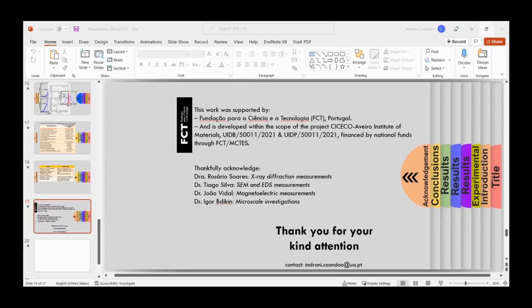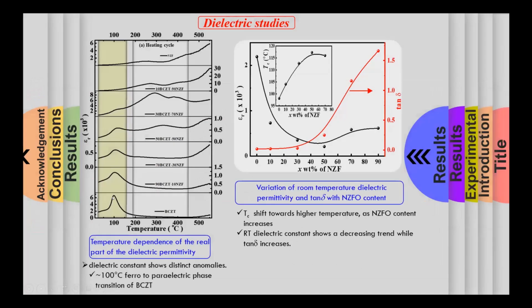Okay, thank you. And another thing, madam, in your graph, you are saying that when you add the nickel zinc ferrite, then the peak decreases. Madam, why does this peak decrease? In which graph? I didn't get you. Nickel zinc ferrite, you show in the graph, when you add it, then the peak in the graph decreases. Here we are increasing the magnetic phase. So correspondingly, the piezoelectric phase is decreasing. Like see, 90 BCZT, 90 piezoelectric and 10 magnetic; 70 piezoelectric, 30 magnetic. So as we are going in this direction, the piezoelectric phase concentration is decreasing. So obviously, its effect will slowly, gradually weaken. It will be the magnetic phase now that will dominate.